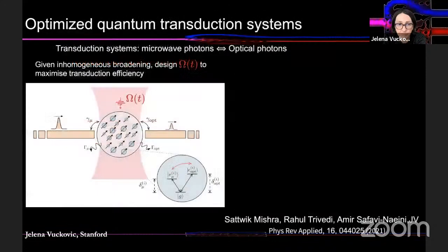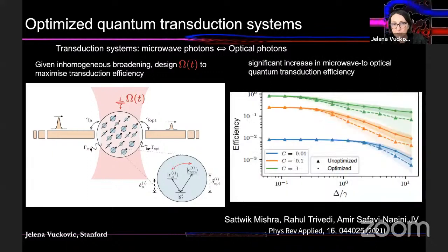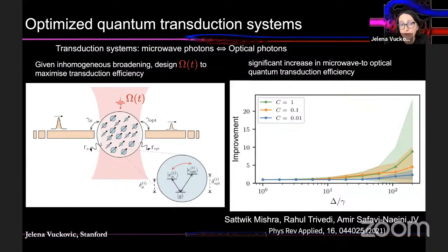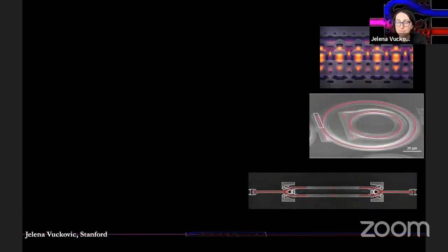And we've shown, for example, that for the quantum transduction problem, where you're converting a single microwave photon to an optical photon, where the efficiency of this problem is limited by the inhomogeneity of this solid state ensemble, you can significantly increase efficiency by applying a single optimized driving signal to the system. And we've shown that we can improve the efficiency by a factor of about 20 for realistic system parameters, simply by applying a single set of electrodes and modulating all of them at the same time with this complicated periodic signal, which is recovering their collective behavior.